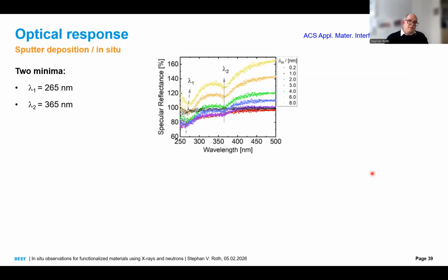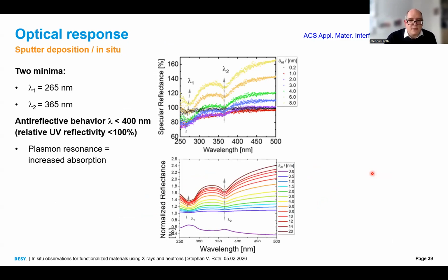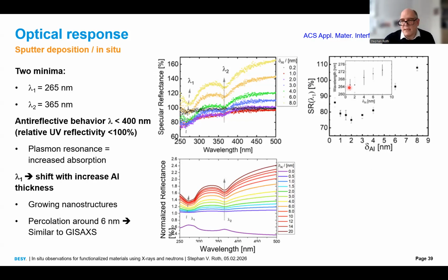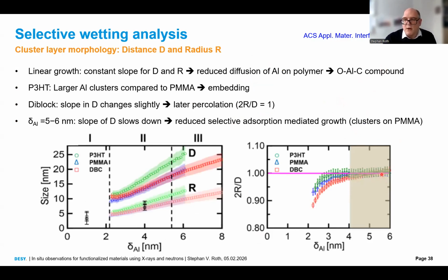Now we look at the specular reflectance. We see 2 minima called lambda 1 and lambda 2. One stays constant, the other one shifts. It shifts with deposition, and therefore this is induced by the plasmon resonance, and we can easily correlate the spectral reflectivity with the deposited aluminum thickness. Again, we see an anti-reflective behavior for small deposit thickness, and we see that this side maximum plasmon resonance shifts with deposited amount of aluminum. What we also see from the simulations, we see a percolation around 6 nanometer, and here we have indicated this here at 6 nanometer, all of our clusters are percolated. Good, nice.